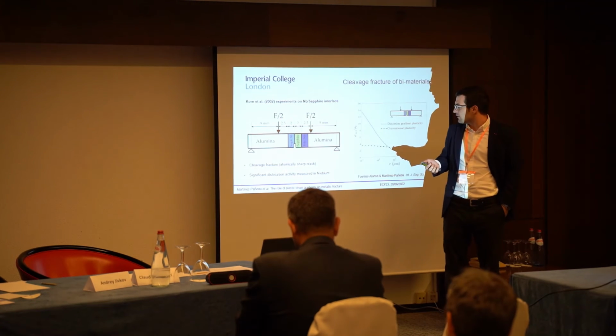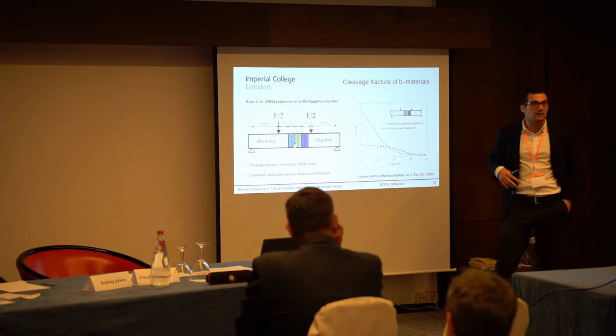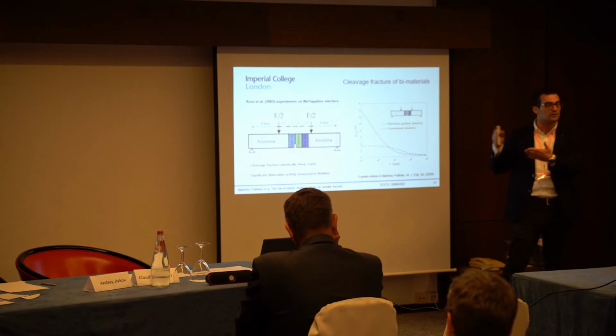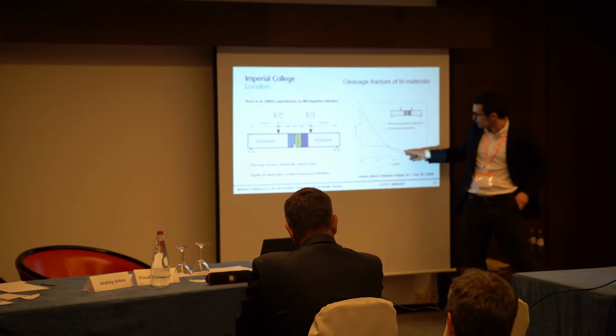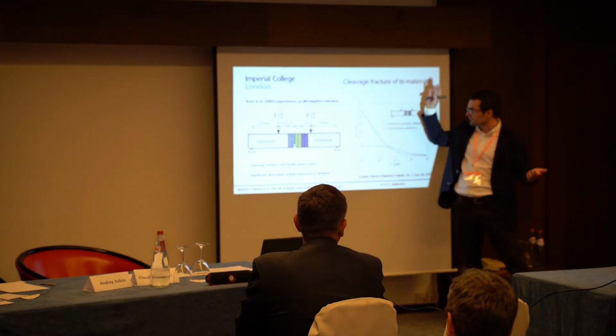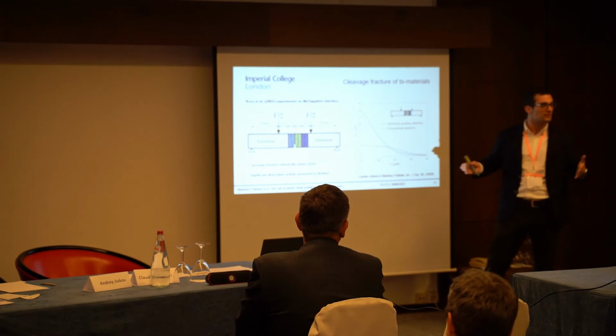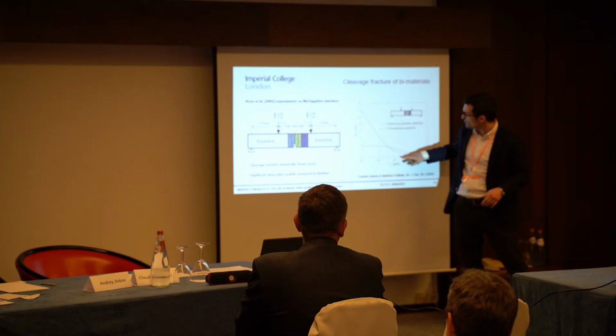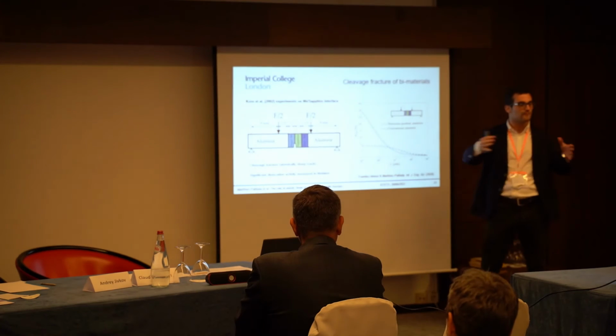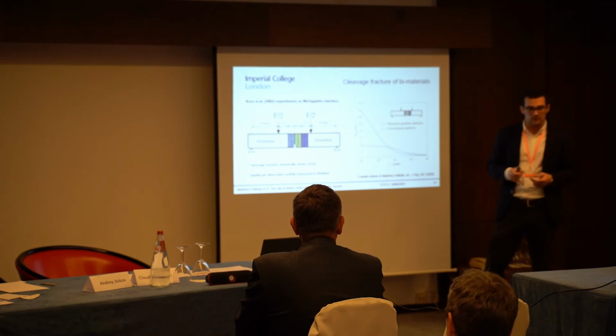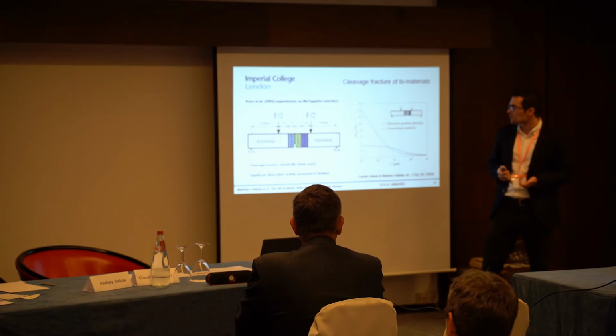And then, of course, if we compute the crack tip fields for those conditions, for the critical load at which failure was observed, then we see that with conventional plasticity, our stresses are far off. No way you can get atomic decohesion there. But if you take into account these gradient effects, your stresses are sufficiently large over a relevant distance to rationalize this atomic decohesion.